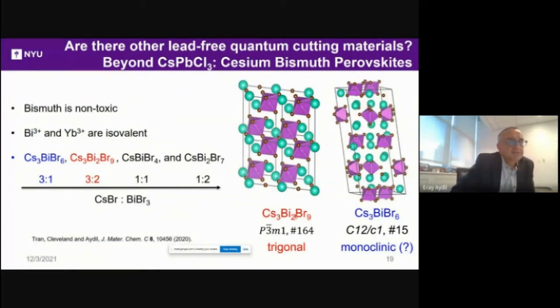I'm going to focus on two of these. One is cesium 3 bismuth 2 bromine 9, which is a trigonal material, and the other is cesium 3 bismuth 1 bromide 6. There's a little bit of controversy about its structure. We and some others think it's monoclinic. The only thing I'm going to point out is that in the cesium 3 bismuth 2 bromide 9, the octahedra are not corner connected. They're just distributed and independent. Whereas in this material, they are corner connected. You can't see all the connections here, but if I were to rotate this, you would see all the other connections too.